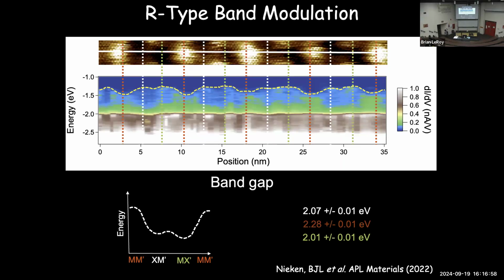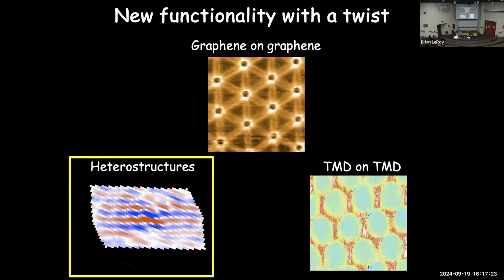And a similar thing will happen in the R-type materials here. I'm only showing the valence band because the conduction band doesn't have any modulation. So all of the band gap modulation occurs in the valence band. And you can see it's on the order of 200 millielectron volts, 0.2 eV. So this is a very strong effect in this modulation of the band edges in these materials when you go to the heterobilayer and mix different materials together.